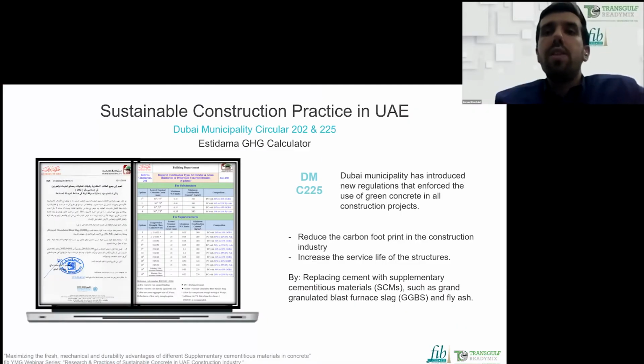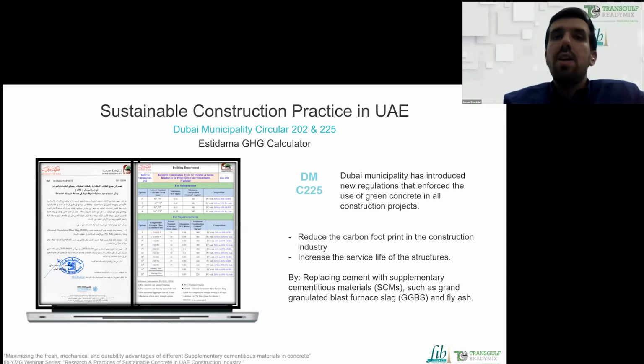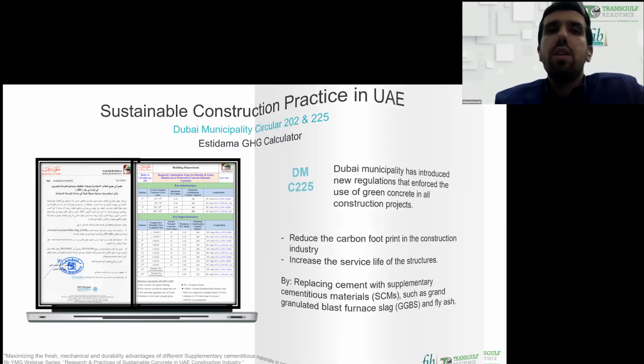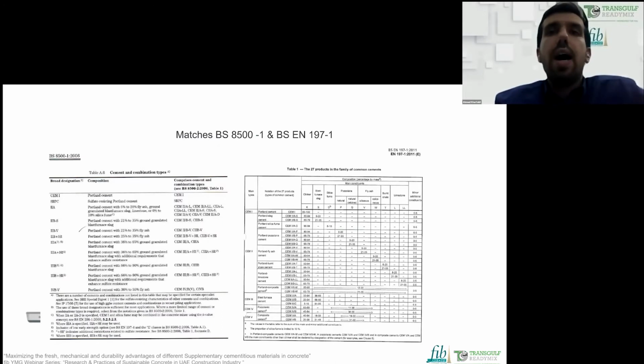Mr. Fadi also highlighted the Dubai Municipality Circular, so I'll go quickly through this. As highlighted by Mr. Fadi, the main points are to reduce carbon footprint and also to increase the service life. The target here is usually a minimum of 50 years for the structures. And this is based on BS 8500 and BS EN 197.